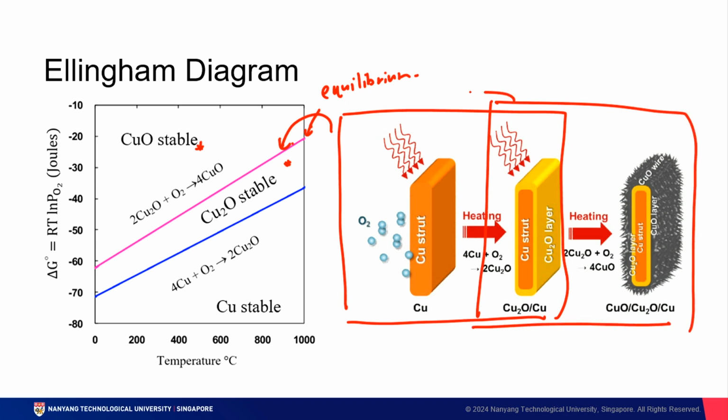This reaction can be represented by this blue line, where below this Gibbs free energy, at these temperatures, copper will be stable. So, in this very simple Ellingham diagram, people who work in factories, such as metallurgists, will be able to take reference very quickly, without doing massive amounts of calculation, the necessary temperatures in order to, say, keep copper stable, especially if they are trying to extract copper.